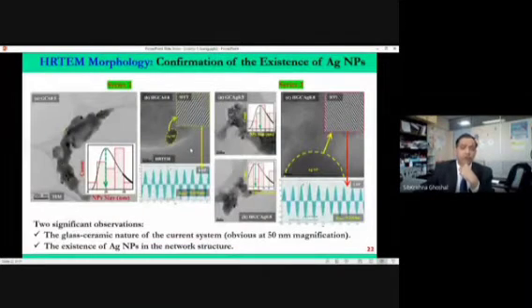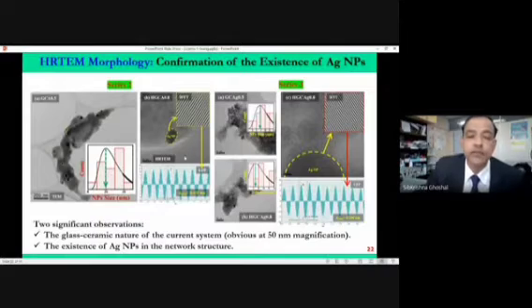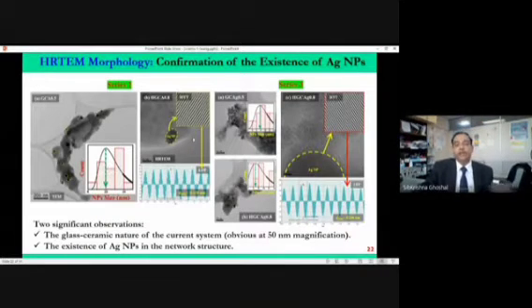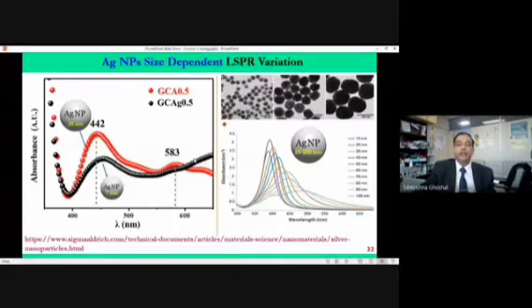Well, how do we know nanoparticles are formed? Then we take the glass ceramic, then we do TEM and also HRTEM, again measure the SAED, fast Fourier transform, then we see again very nice lattice fringes are formed, and that's how we get the nanoparticle. So it is ensured that the nanoparticles and crystallites are there.